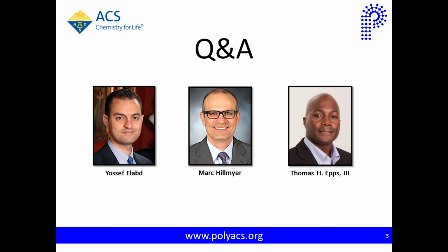Now, one of the problems with PEO, and typically what people are still doing, is seeing whether I can dope in either ionic liquids or other types of groups to try to improve the native conductivity of the PEO-based systems. In those cases, I think the jury's still out in terms of how they behave with long-term stability. So for the neat PEO systems, they're pretty good under most conditions, but when I start putting in additives, then I do have to worry about that.